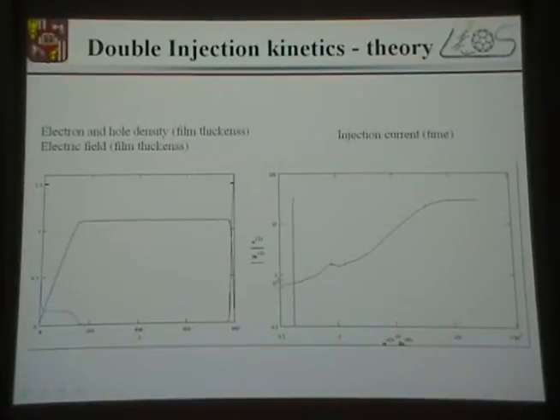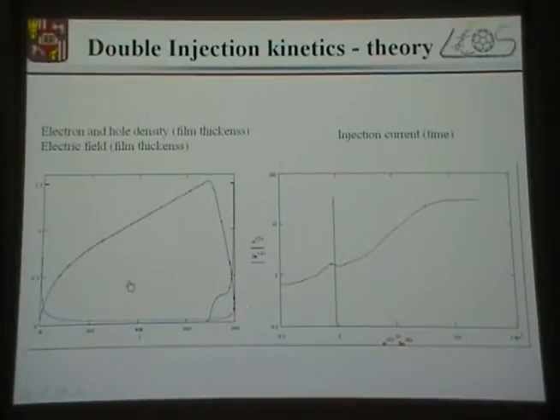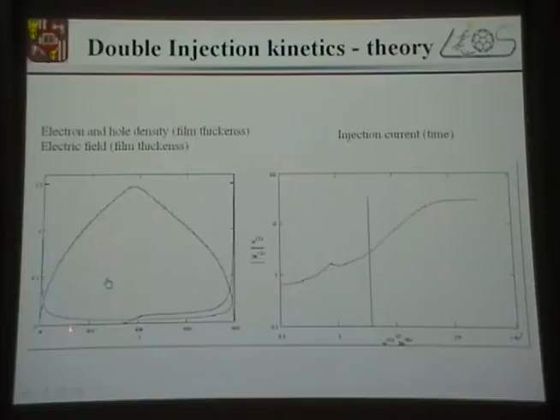And as you see, in the very beginning, so this is the assumption, the calculation. This calculation is simply done by solving the Poisson, kinetic and the continuity equations, with the assumption that we have a bimolecular recombination. So extremely simple, not many assumptions done. It's assumed also that electrons are 10 times faster than holes. And in the beginning we see that electrons are getting injected into the film, and then they reach the opposite electrode. And that's exactly when the electrons reach the opposite electrode, in the current kinetic we have the characteristic kink. Then electrons are being constantly injected through the film, and the holes come in, and then the holes reach the electrode.